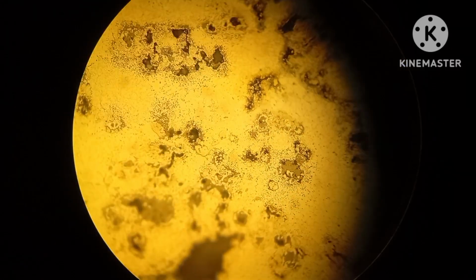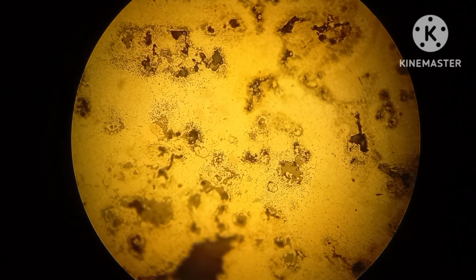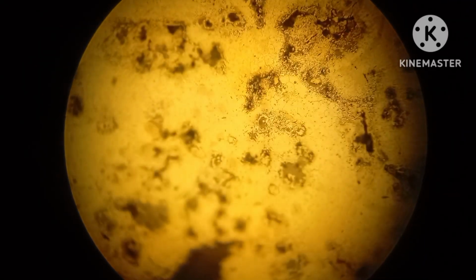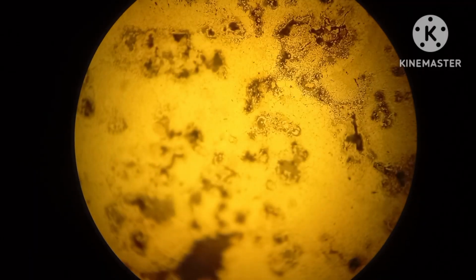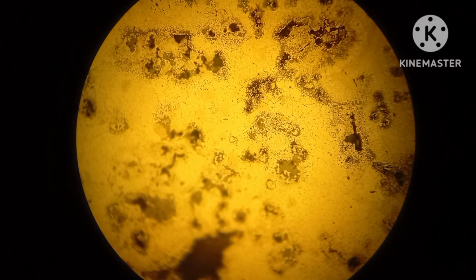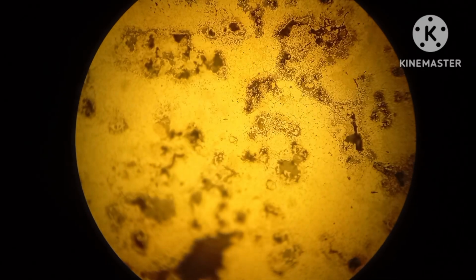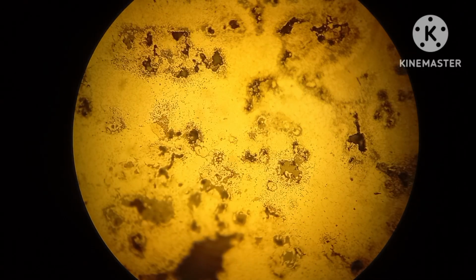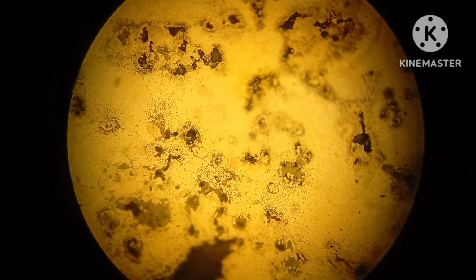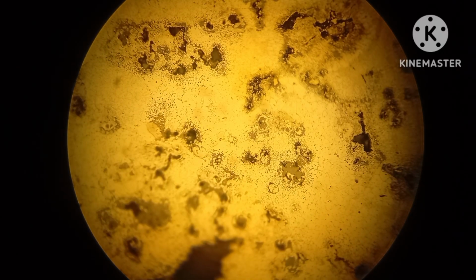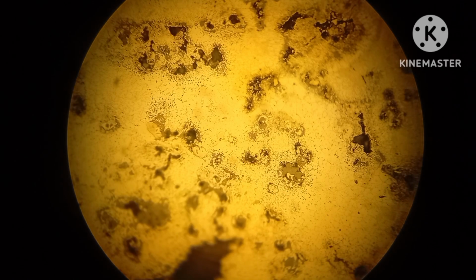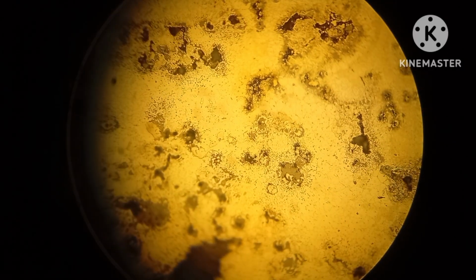We have the 500 optical magnification, and you can still see the carbides and some grains. I used the Nital 5%. It's not so aggressive as the hydrogen peroxide. I will show on the screen the image that I get with the microscope camera. It's a compound image due to the relief on the surface.